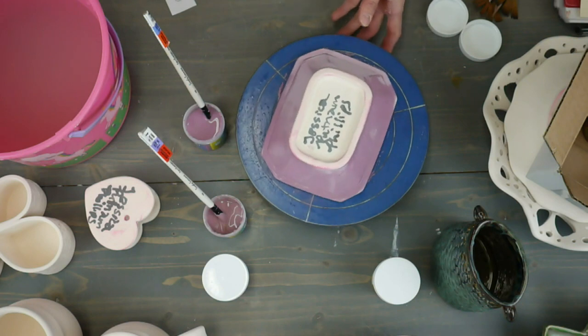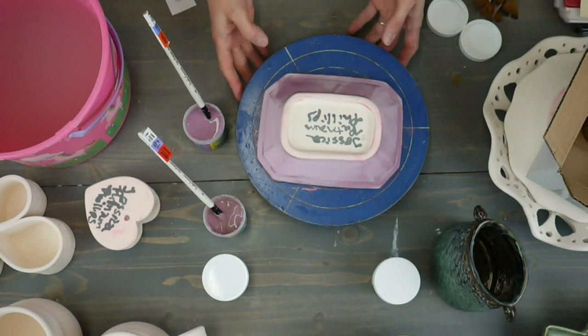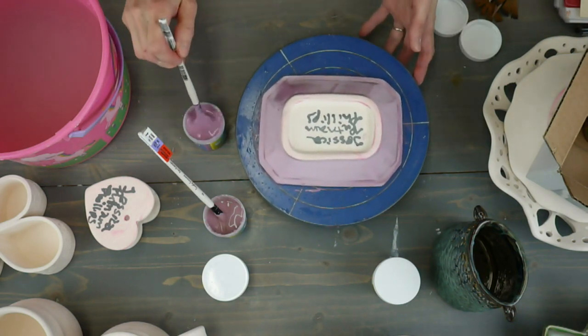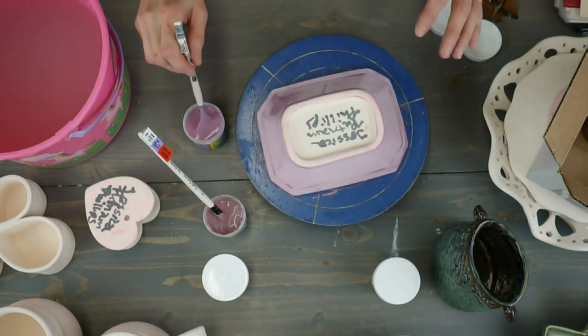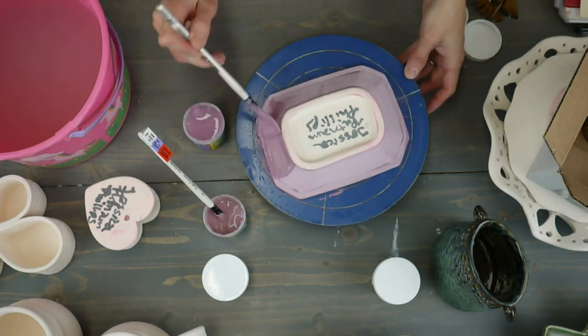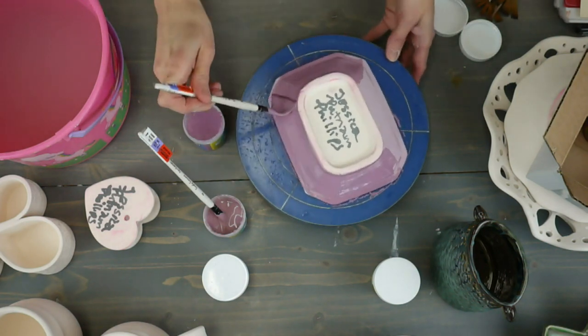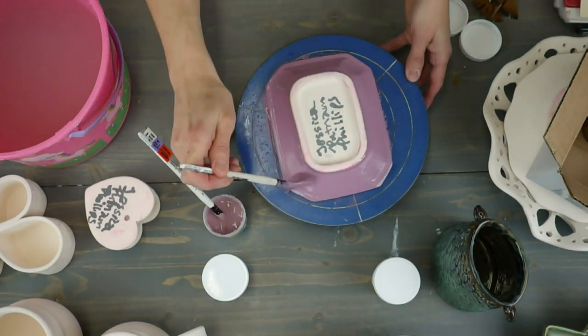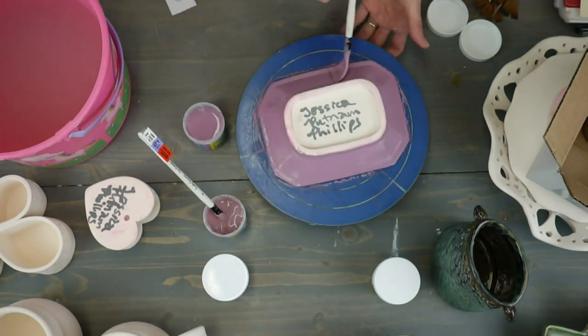And I saw someone said, do you need a kiln to do this? These are stoneware glazes. They are meant to be fired to cone 5, cone 6. The temperature will depend on what you're using for clay. I'm using Laguna B-Mix, which is a cone 5 clay. So I go to cone 5. With this load, I'll go to a hot cone 5, so that would be a little hotter. If you look at cone temperatures, it's not like 2167 is cone 5 and then 2168 is cone 6. You usually have 30 degrees between, so you have a little wiggle room there.